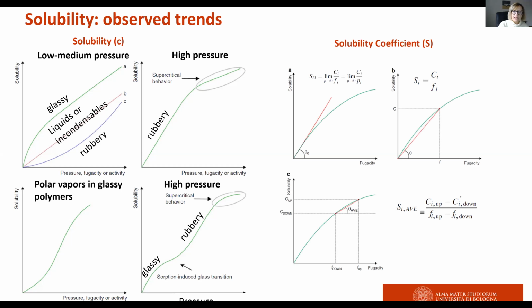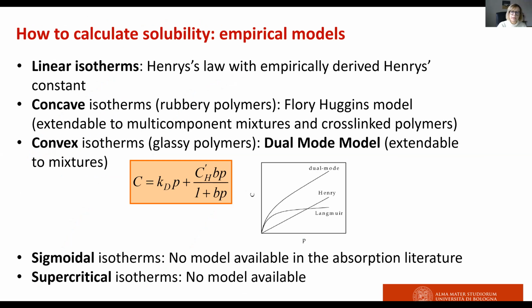Luckily enough, we have several models available to predict or to correlate solubility, and in this slide I'm reporting only the empirical ones. You can of course use Henry's law with experimental data for the linear isotherms. You can use activity coefficient models for the rubbery polymers. For the glassy polymers, there is an empirical model which is called the dual mode sorption model, and is the sum basically of a Henry's law term and of a Langmuir term. There is no empirical model available to represent the behavior of sigmoidal or supercritical isotherms.